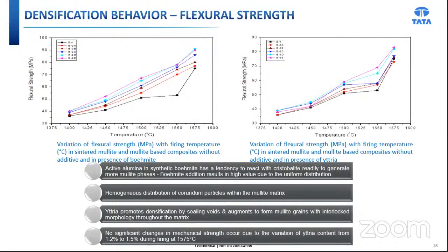It is reflected from the figure that, in comparison to yttria, boehmite addition results in high bending strength, which may be due to the uniform distribution and also interlocking of the secondary mullite grains throughout the matrix. Since active alumina in synthetic boehmite has a tendency to react with cristobalite readily to generate mullite, even at 1550 degrees centigrade, a remarkably high flexural strength of 78 to 85 megapascal is achieved.